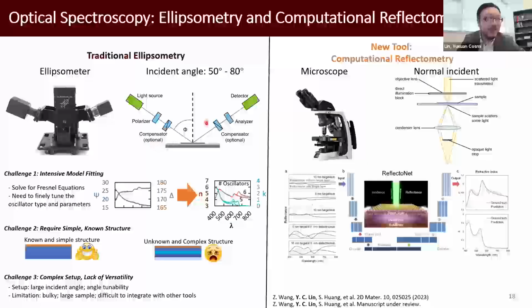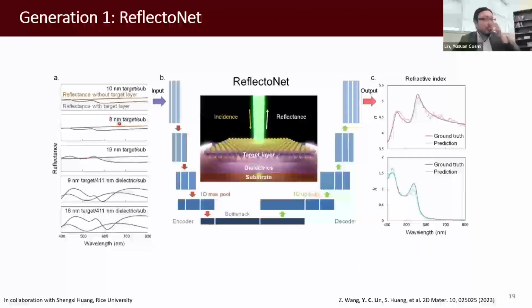So instead of varying the angle in our input, maybe it's easier to show in the next slide. In the input, we put 2D materials on different substrates. Those substrates are just multi-layer dielectrics. Those are just random numbers we deposited or tried. So the network itself doesn't know, but it gives you the complexity or the tuning knob. And then we collect maybe 5 different reflectance spectra for the same material on different substrates, and we use that as the input. Then we train the network for the output. It is able to predict the N and the K of this material.